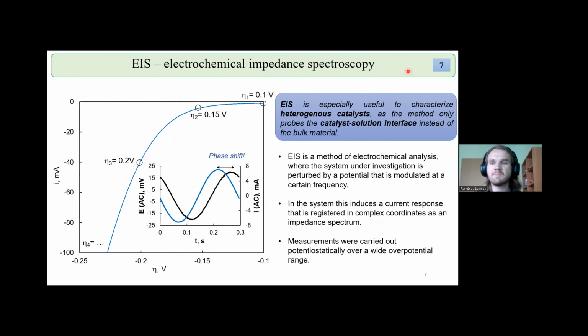Yes. Now, because the surface area is difficult or impossible to measure in certain films, we use electrochemical impedance spectroscopy. Electrochemical impedance spectroscopy is especially useful to characterize surfaces, that is to say, reactions that occur on the surface and heterogeneous electrocatalysts. In this method, effectively what we do is apply a certain perturbation on the applied potential in potentiostatic electrochemical impedance spectroscopy. So the potential is modulated by a certain frequency. There are different frequency points. And in the system, the response is a current density, a current that also follows the modulated potential. There's a certain phase shift between them.